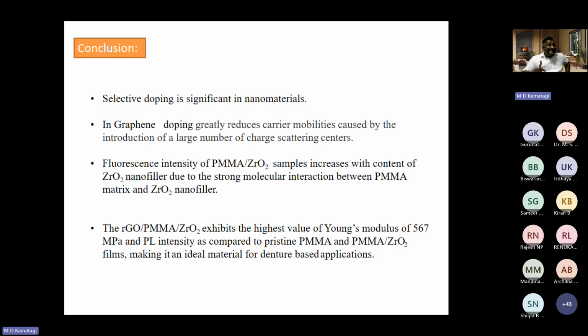In graphene, doping greatly reduces the carrier mobility caused by introduction of a large number of charge scattering centers. In case of the composite films, the fluorescence intensity of composite samples increases with the content of nanoparticles, due to a strong molecular interaction between the PMMA matrix and ZrO2 nanofiller. In case of the reduced graphene oxide, polymer and metal oxide nanocomposites, we have seen that the PL intensity increases for a particular value of graphene oxide, as well as the Young's modulus is more for 1% of graphene oxide and 3% of ZrO2 nanoparticles based applications.